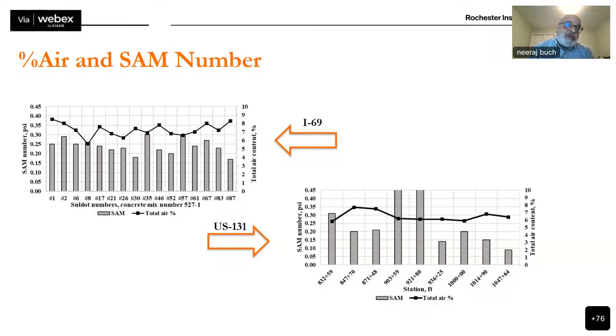And a typical SAM number or a super air meter number is about 0.2. So if the concrete is within 0.2 and 0.25, then the concrete has the right volume of air as well as the appropriate spacing between the air bubbles that are entrained in the concrete. So for the most part, both I-69 and US-131, based on our sampling and the data that we were collecting, showed that the distribution of the air bubbles and the volume of air were adequate to resist freeze-thaw damage. So again, from the volume of air and distribution of air bubbles, there was nothing that was alarming or something that should have given us any pause.